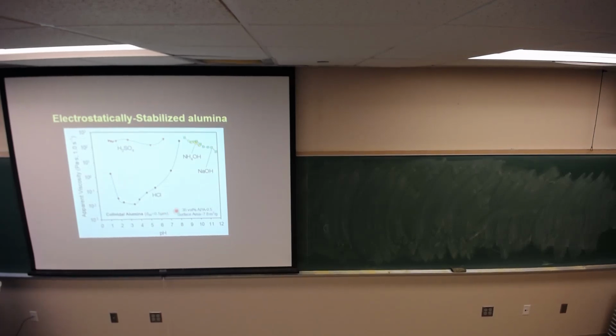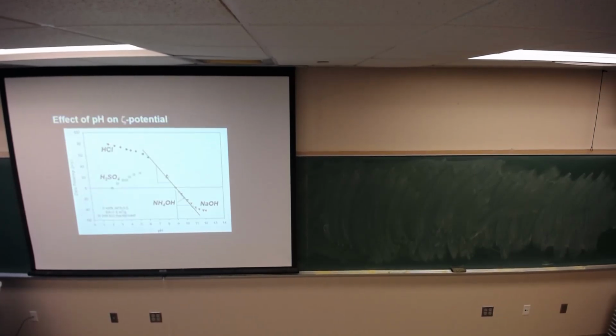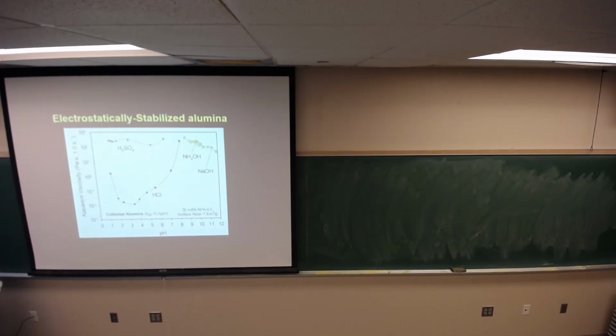This is at 35 volume percent, right? So what does that mean? Oh, well, if I go back to this, this is at 5 volume percent, 35 volume percent. I have 7 times more surface area, you could argue, in this case than I do in the other case. That means that I'm going to have to add 7 times more acid or base to change that pH. So that means the concentration of counterions that comes in with that acid or base is going to be significantly higher, plus I have less water, right?